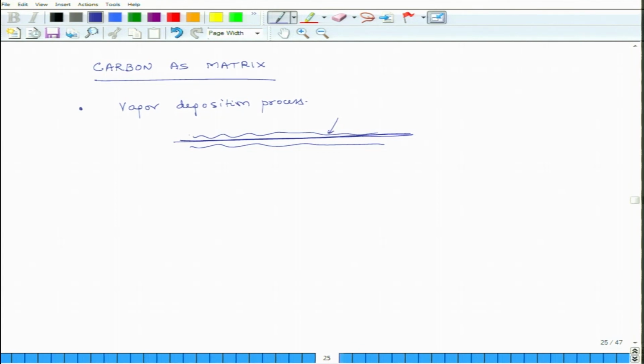Here what you do is you have pyrolytic graphite, okay, and then using some reactive process you deposit slowly the graphite over the fiber. And these guys can take really very high temperatures. Use temperatures can be as high as 2700 degrees centigrade. And once again, this is used in nose cones for missiles, re-entry vehicles and things like that.